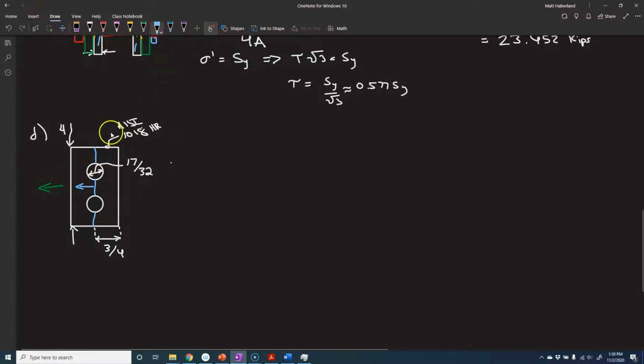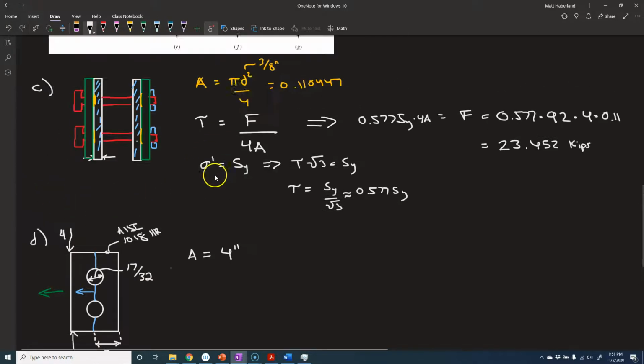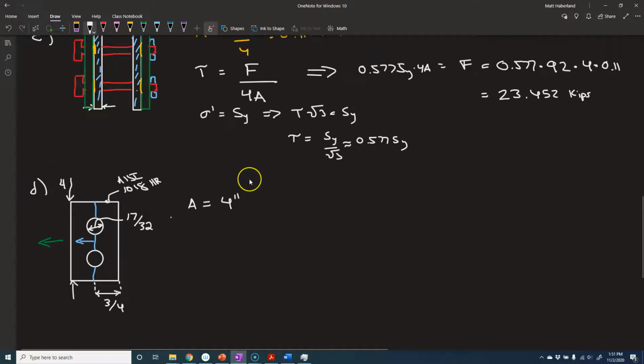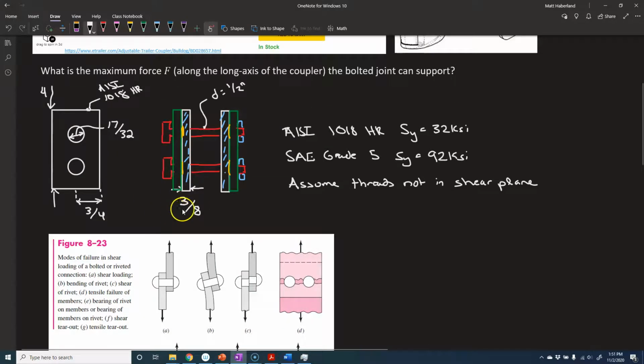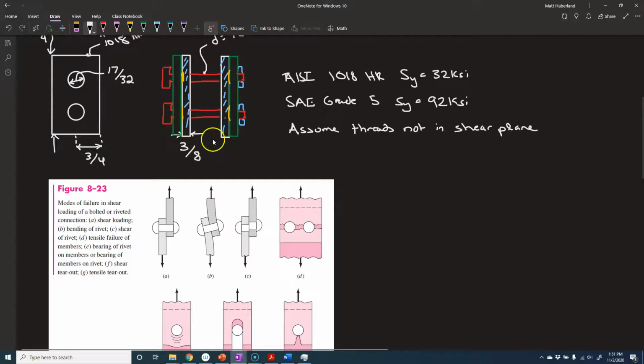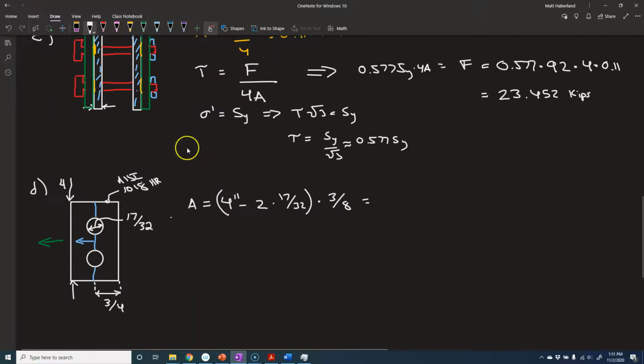Now what's that area? That area is this 4 inches, not to be confused with a factor of 4 over here due to the number of bolts, but 4 inches from top to bottom minus 2 holes. And those holes are 17/32. So that's the total amount of distance we have, or length in this direction, times the thickness of them. And the thickness of them is 3/8 of an inch. We saw that these are 3/8 inch thick. And also note that there's 2 of them. They'd both have to separate at the same time. We're going to assume that they carry the load equally between the two. So we're going to have to take that into consideration. But the area is just the area of a single one.